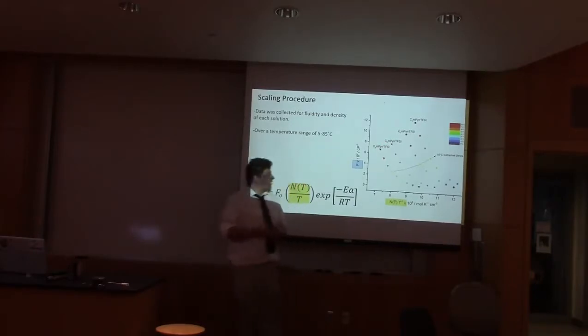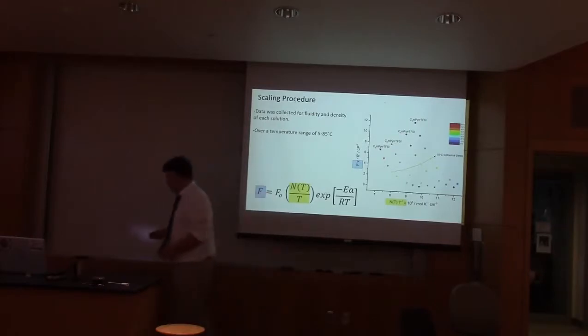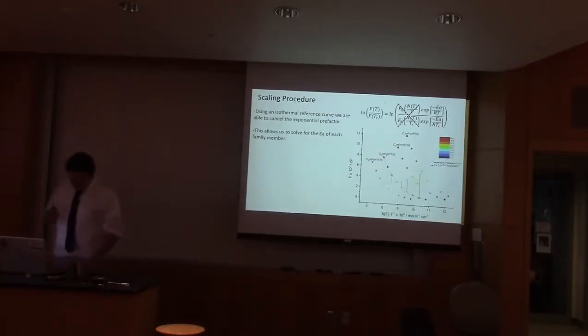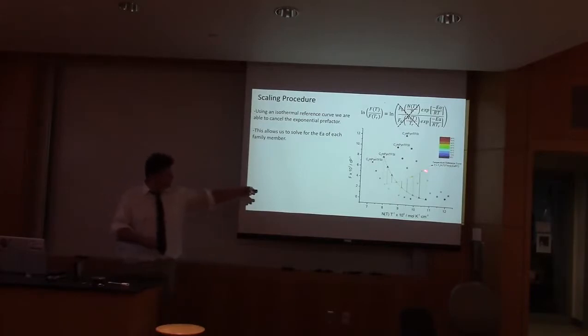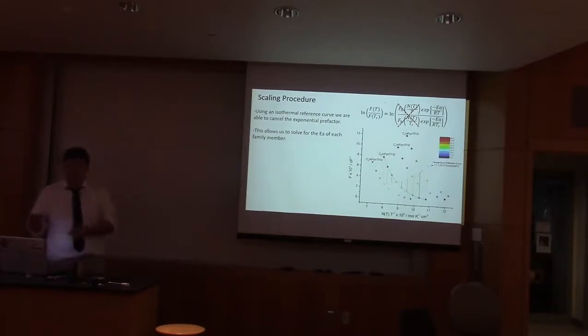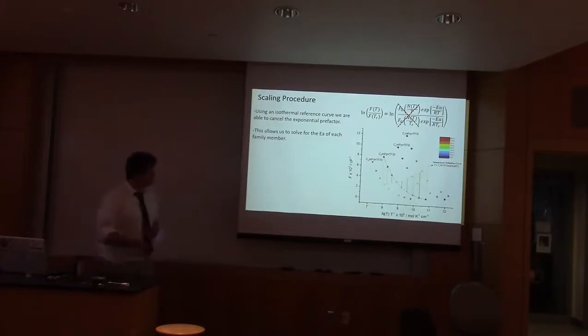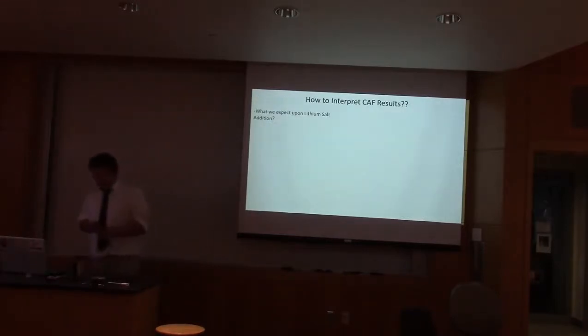From there, now that we have the data for each individual room temperature ionic liquid, we were able to use a method called the scaling procedure in order to cancel out the exponential prefactor, using a temperature reference curve, in this case 55 degrees Celsius, and solving for the C6 end member. We are then able to solve for the activation energy by itself. Once we solve for the activation energy, we are able to determine the value of the exponential prefactor. Before I get into the results of our data for fluidity, I want to talk about what we would have expected to see using the CAF.